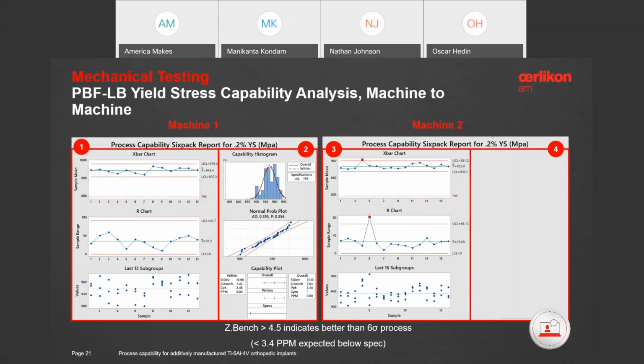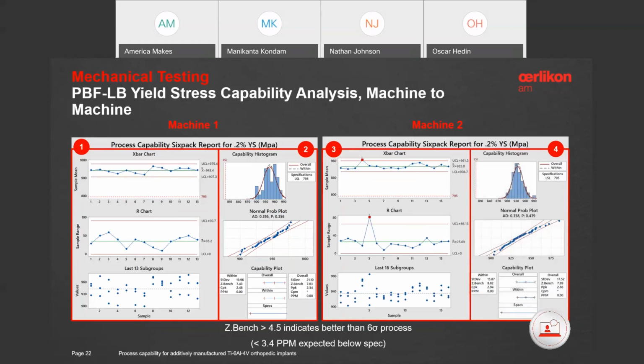And also we checked for the R bar charts to see the variation in the data. Again, these two charts look well and under control. Proceeded with calculating our normality of the data. Even here, we observed that the data was very well under the normal distribution. So we went ahead and calculated our process capability indices. Here as well, the CPK and PPK values were well ahead of 1.33, and the z-scores were also greater than 4.5, indicating a process which is Six Sigma level.